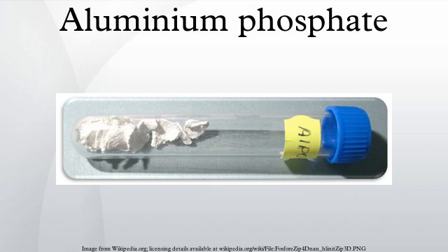A typical preparation of an aluminum phosphate involves the hydrothermal reaction of phosphoric acid and aluminium in the form of hydroxide, an aluminium salt such as aluminium nitrate or alkoxide under controlled pH in the presence of organic amines. These organic molecules act as templates to direct the growth of the porous framework.